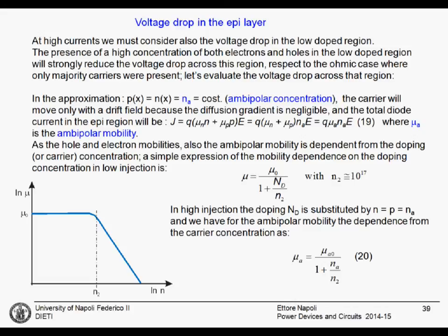We were able to calculate the IV characteristic of the diode in the low injection and in the high injection regime. We are completely neglecting at this point the voltage drop on the middle layer. We are saying that the voltage drop on the diode is just a junction, but the thick low doped region is not considered. This is not possible, this effect is not possible to be neglected when the current starts to be significant. There will be a voltage drop on the low doped region, and this is possibly even the biggest part of the voltage drop.